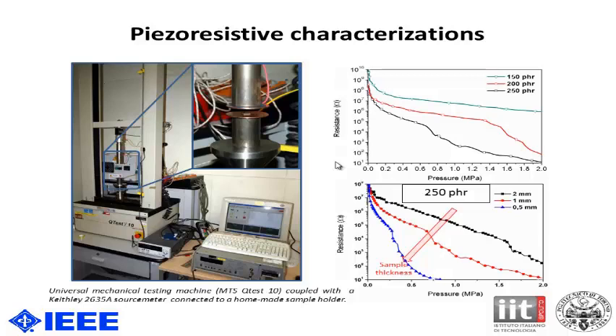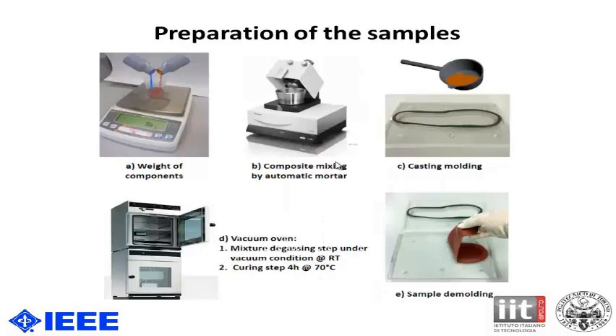We tried to vary the thickness of the sample, and we decided that the best one is 1 millimeter thick, because the resistance values are well spread among 7 orders of magnitude, and especially they are quite good for our operating range. The preparation of the sample was made by weighing the components first and then mixing them in an automatic mortar. After the casting molding, we cured it in a vacuum oven at 70 degrees Celsius for 4 hours.